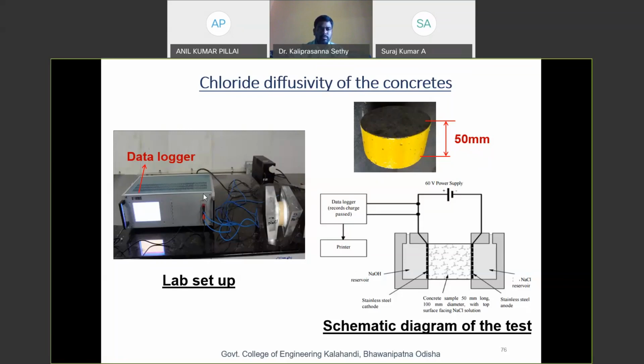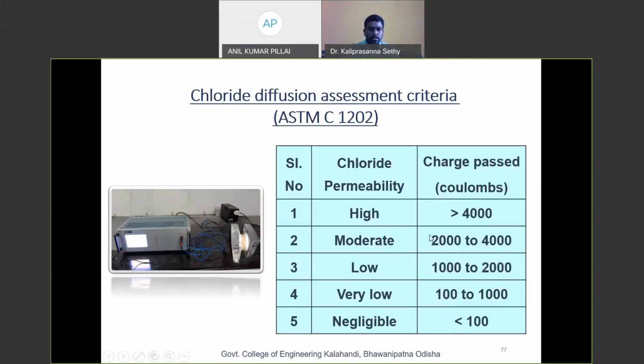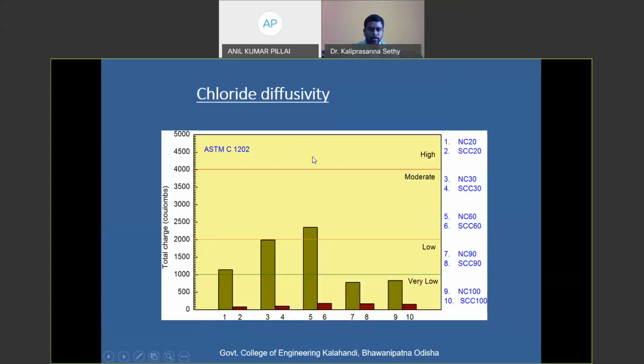And this is the lab setup for this chloride diffusivity test. You can see there are two reservoirs. One contains NaCl solution and the other contains NaOH solution. By allowing the current to pass through this, we charge the ions and try to attract the ions to each other. By using this data logger, we record all the charge passed through it. And by this, we calculated all the chloride diffusivity values.